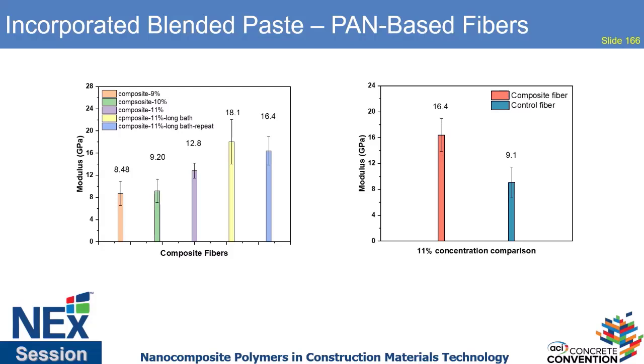But what you can see here is as I increase the polymer, which means I'm decreasing the nanotube content, because I have the blended phase and I have such a good interaction, that actually extends out. The polymer keeps forming a larger and larger interface. So I'm actually getting better reinforcement of the fiber. So I'm using the nanomaterial in a way to help the polymer to self-reinforce itself. I'm not just trying to add more and more of it. I'm trying to make sure that the interaction really translates to the polymer matrix.